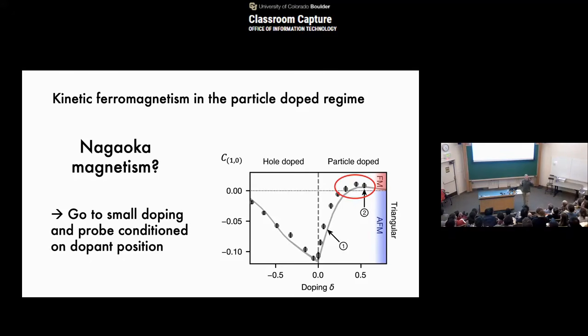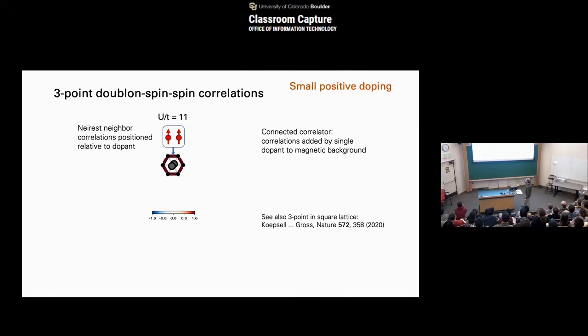But the nice thing is with the microscopy, we can now go ahead and just see what a single particle does. Meaning we can do simulations with a few particles, and then we can take a snapshot and see where the doublon ended up and investigate the magnetic environment around that particle, like 3-point correlation functions. And so we can directly see what effect a single dopant has compared to not conditioning that measurement on the position of that dopant. So if we find a doublon on a lattice site here, what are the nearest neighbor spin correlations doing around that dopant? And we found here for moderate interaction, the nearest neighbors around that hole are strongly ferromagnetically correlated.